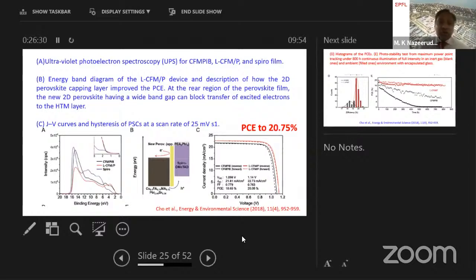So here, by using the UPS data, we constructed the energy level scheme. Based on this energy level scheme, you can see that by shining the light, we create charges in the perovskite, positive charges and negative charges. If you look at the HOMO level of this two-dimensional perovskite, it is well aligned with the three-dimensional perovskite, so the positive charges generated in the perovskite will tunnel to the hole transporting material. At the same time, the electrons generated within the perovskite layer will be blocked here and driven towards the ETL layer. So what is happening here is that we are reducing the recombination because of the presence of this two-dimensional perovskite.